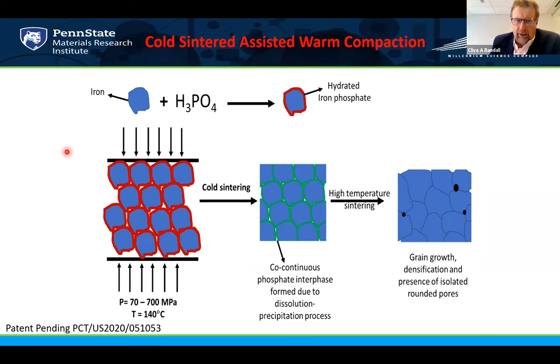So at the moment, we're looking at how to consider a new process. We're using powder metals, and we're using coating technologies. And of course, with powder metals, you've also got plastic deformation. So a lot of the densification, as you get with warm compaction, is plastic deformation. But we're actually having that assisted with a cold sintering step.